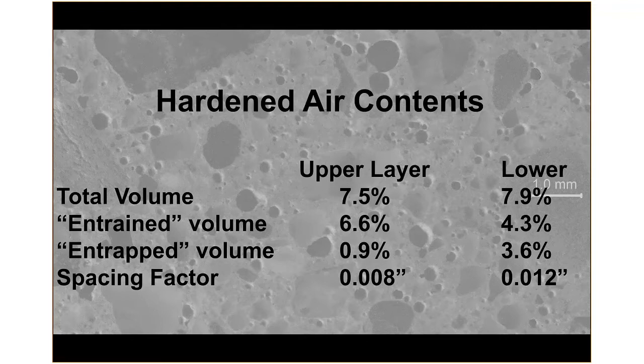The lower under consolidated material, which is the first lift, is 7.9%, again around 8% total volume. The entrained was 4.3%, again void spaces that were intersected during hardened air content testing, and less than 1 millimeter in diameter. The entrapped, very much larger, 3.6, nearly half of that void space is entrapped volume, and some of this is much larger. Now the spacing factor is 0.012, which is just out of the range of freezing and thawing, but still offering some freeze thaw resistance.